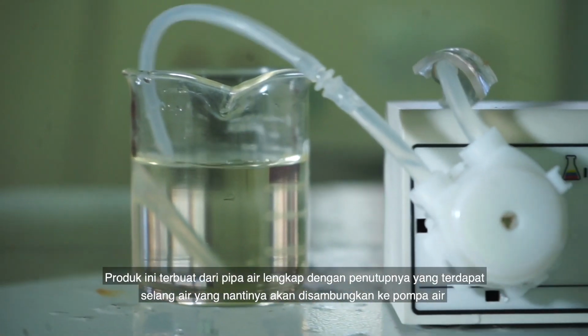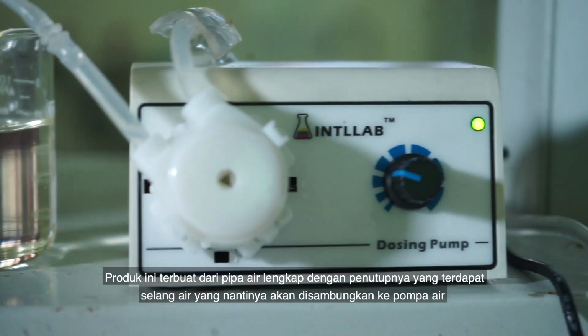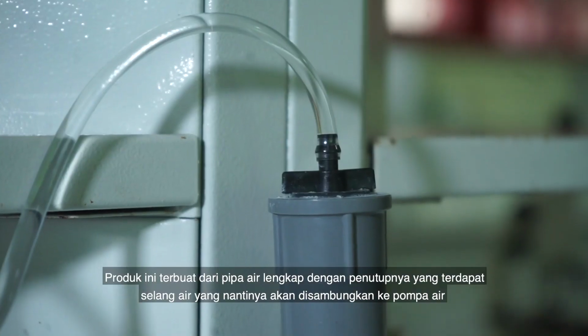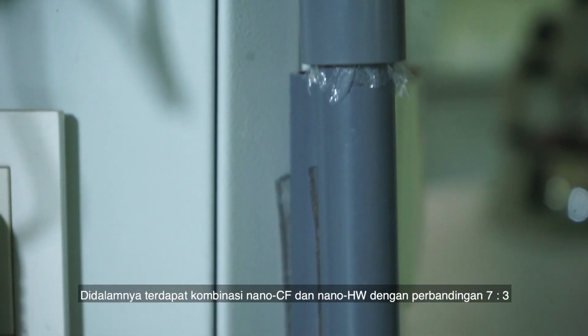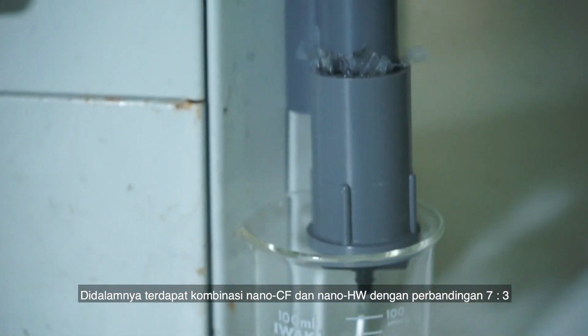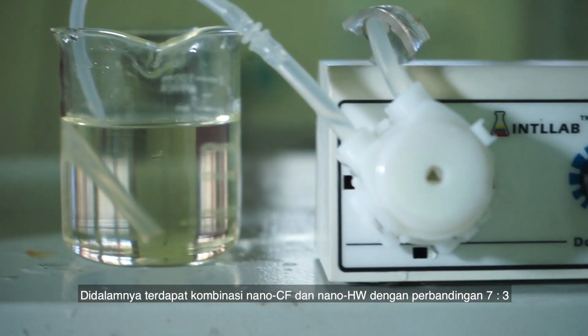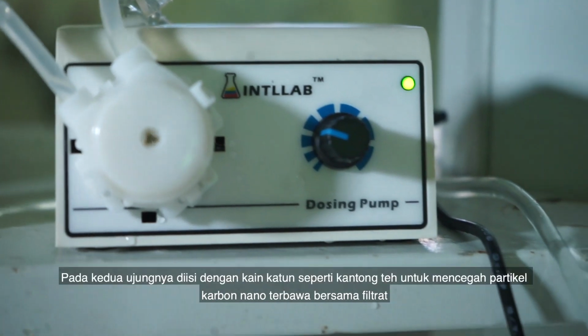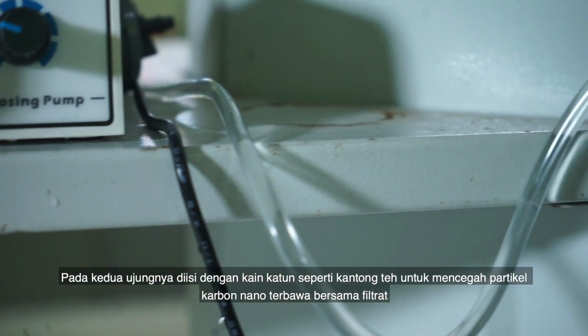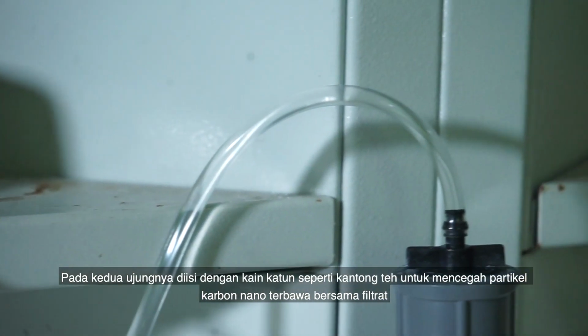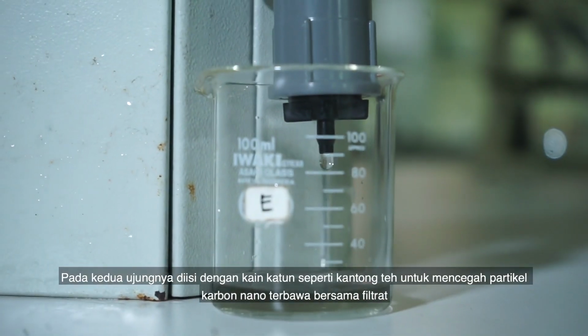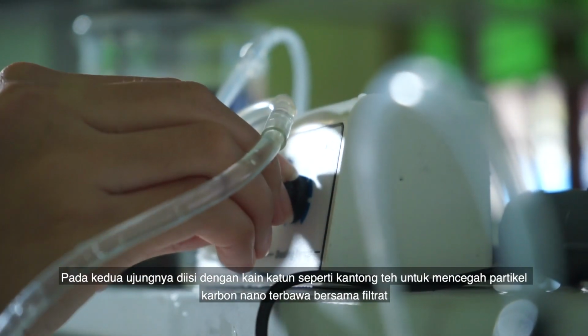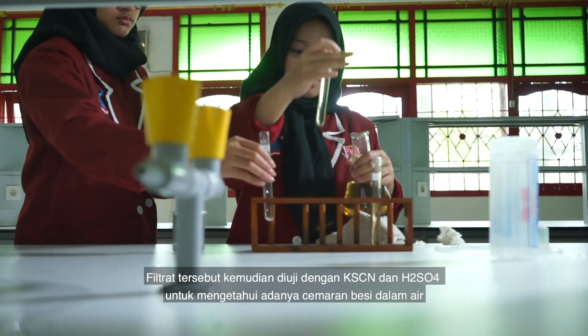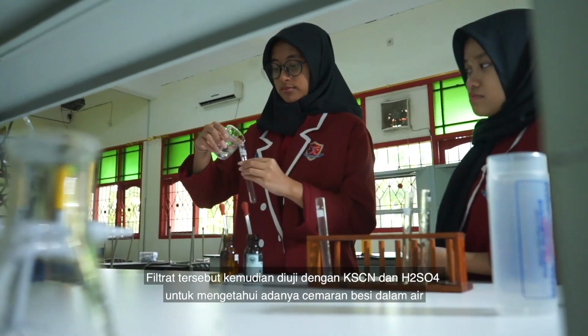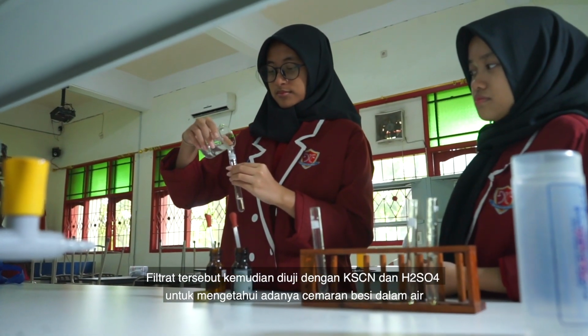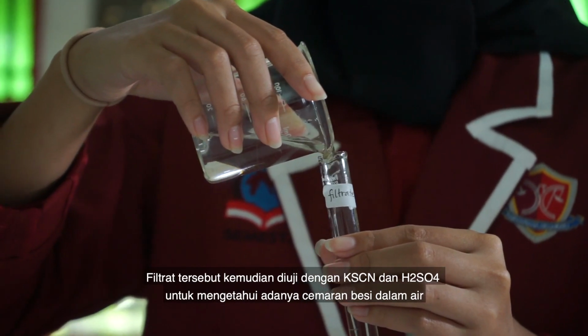This project is made of a water pipe complete with a lid that has a water hose which is connected to a water pump. It contains a combination of nano coconut fiber and nano water hyacinth with a ratio of 7:3. At both ends, it is filled with cotton cloth like a tea bag to prevent nanocarbon particles from being carried along with the filtrate. The filtrate was then tested using potassium thiocyanate and sulfuric acid to check the presence of iron contamination in water.